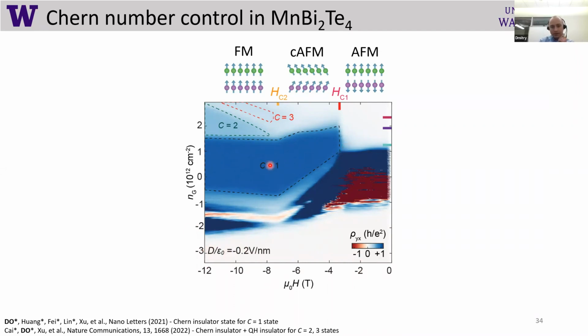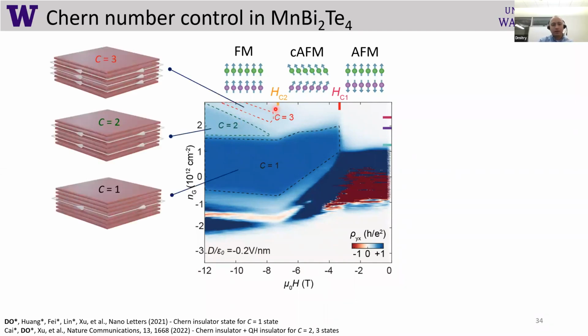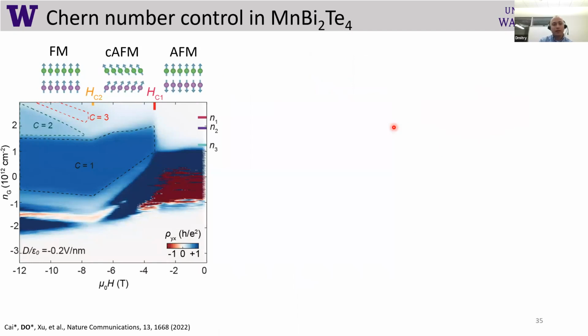So in this map, we can see essentially 3 regions. We can see large region with Chern number 1, smaller region with Chern number 2, which is tilted as a function of magnetic field, and also Chern number 3. And in all these regions, you would have different amounts of edge states. However, the nature of these edge states, even though all of them would be chiral, the reasons why they exist would be slightly different, and I'll talk more about it. And again, at low field, when we are in antiferromagnetic state, our Chern number is 0. We don't detect any signs of edge states. So let's walk through these maps a little bit to understand what's happening.